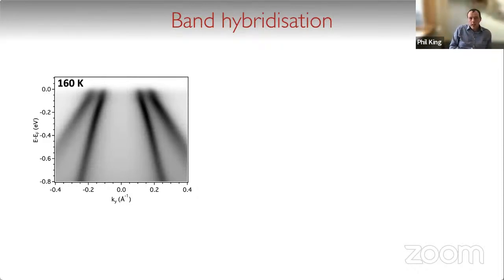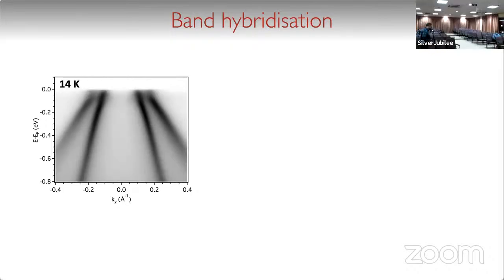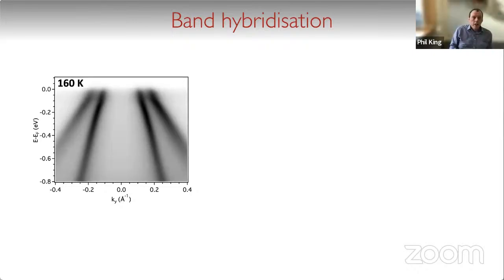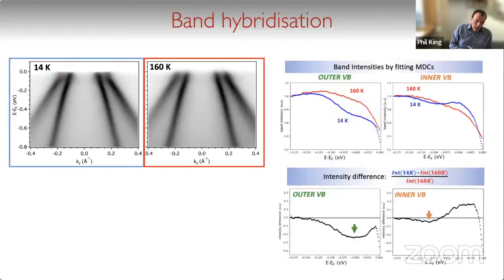So these are measurements at 160 Kelvin above the charge density wave transition, and then at 14 Kelvin below the charge density wave transition. And so you can see that as we cool the system down, there's clear band hybridization happening here at the Fermi level, which has been sort of hidden up to now in the spectral broadening that you tend to get in these monolayer systems. And so, this gives us then the first hint of the mechanism for the charge density wave in monolayer titanium telluride, that this band hybridization here is lowering the total electronic energy in the system.